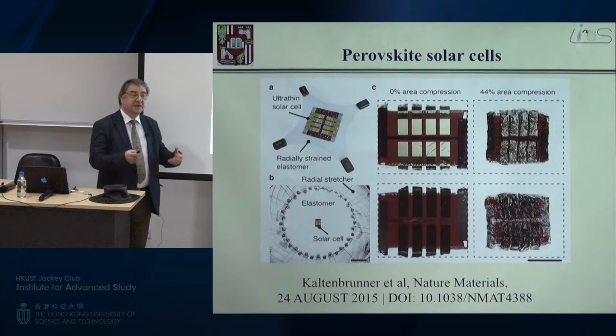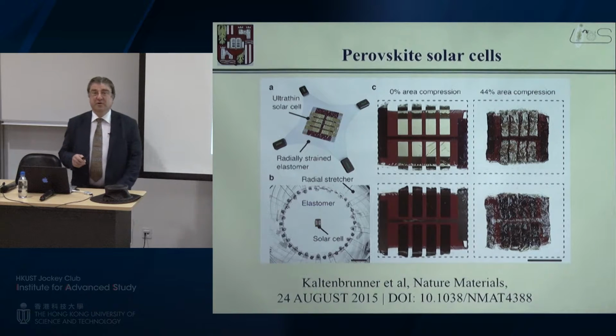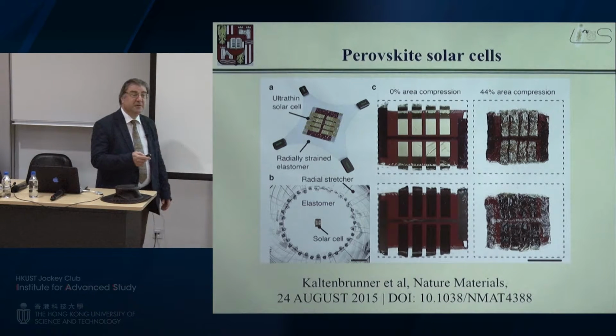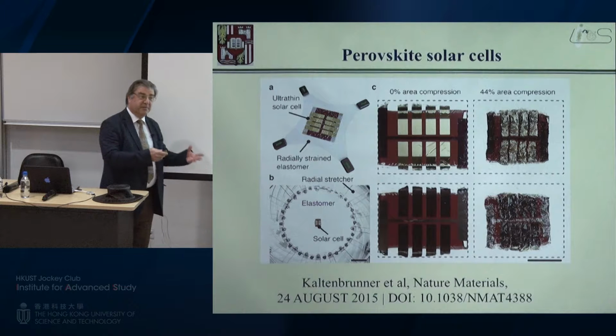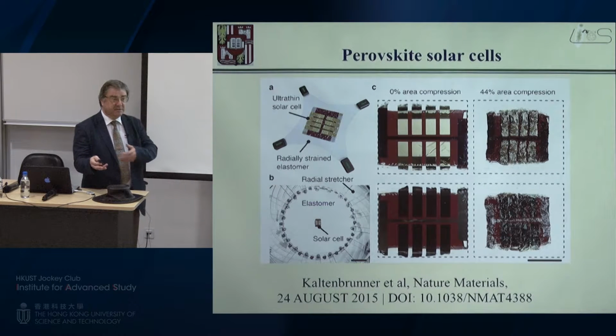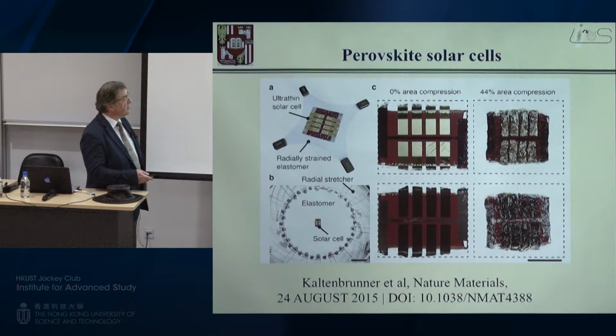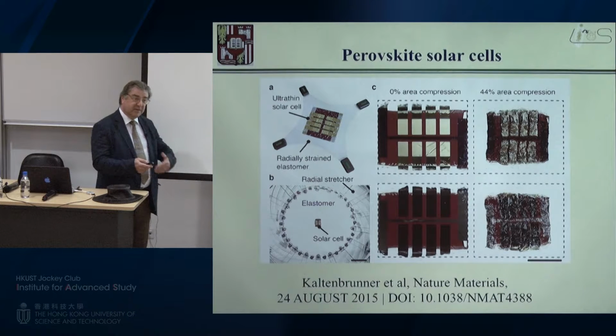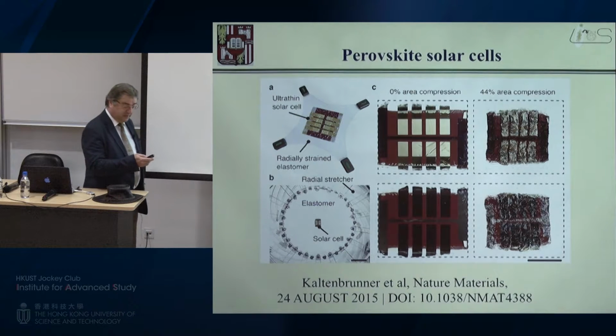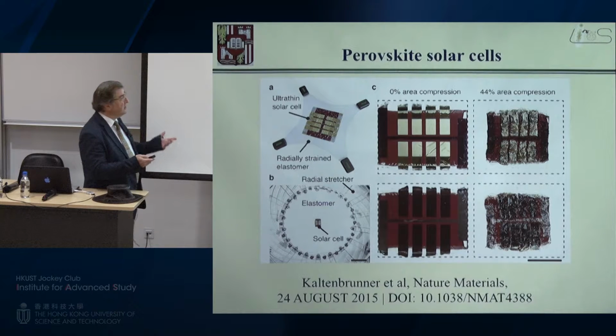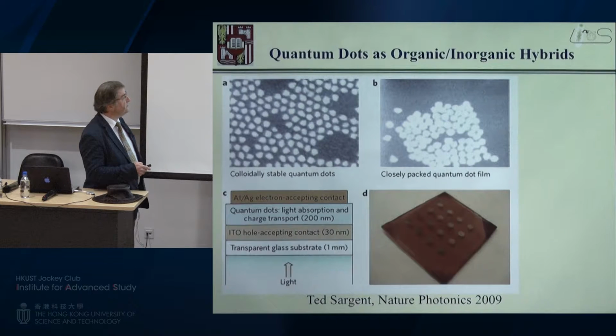I was thinking this inorganic matrix would become very brittle and hinder perovskites from becoming plastic solar cells. But this paper showed last year, and we extended this work more and more, you can indeed use plastic substrate technology on these materials. And since we don't need in these systems, as I showed you, titanium dioxide and sintering, etc., perovskites enter these plastic solar cells.